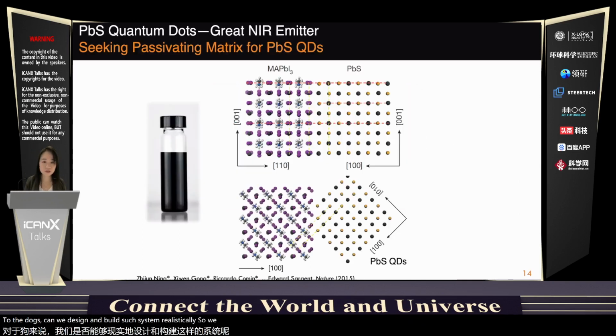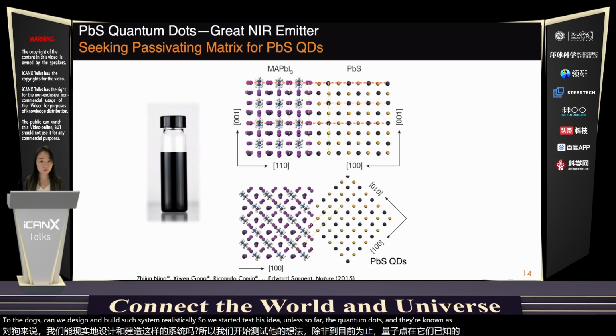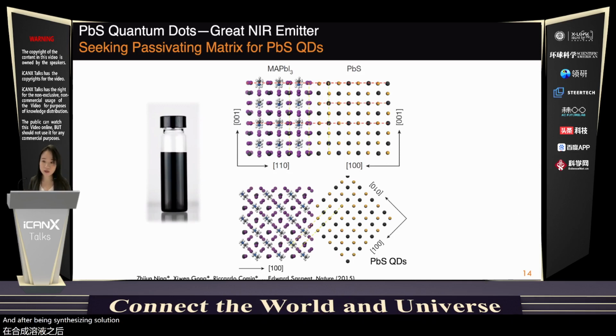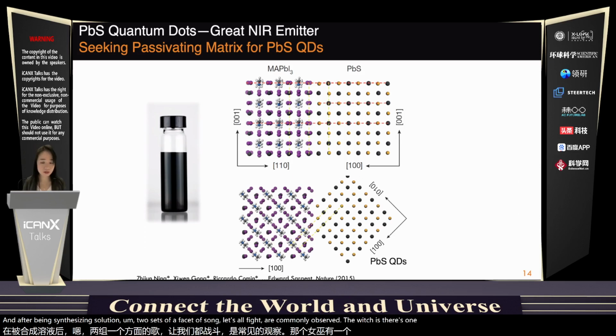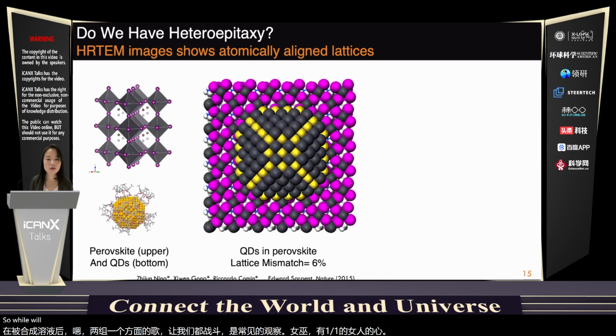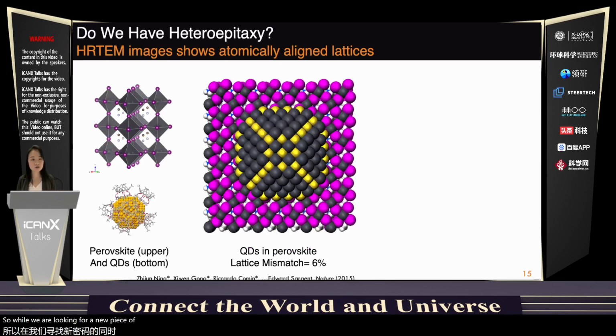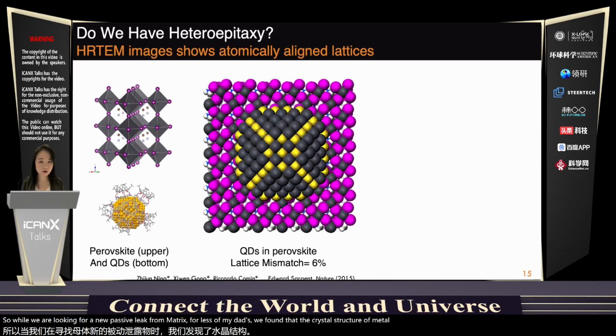So we started to test this idea on lead sulfide quantum dots, which are known as very efficient near-infrared light emitters. After being synthesized in solution, two sets of facets of lead sulfide are commonly observed, which are 001 and 110. While we were looking for a new passivation matrix for lead sulfide dots, we found that the crystal structure of metal halide perovskite surprisingly matches well with these dots.